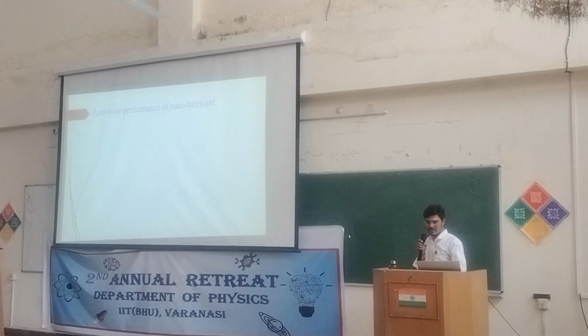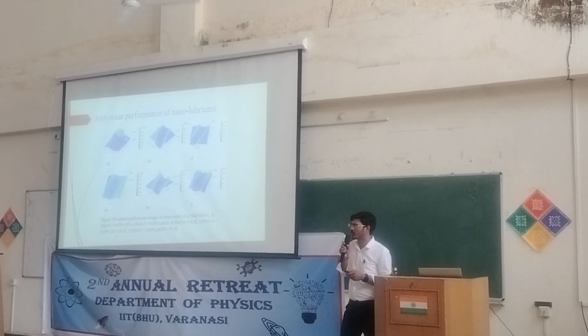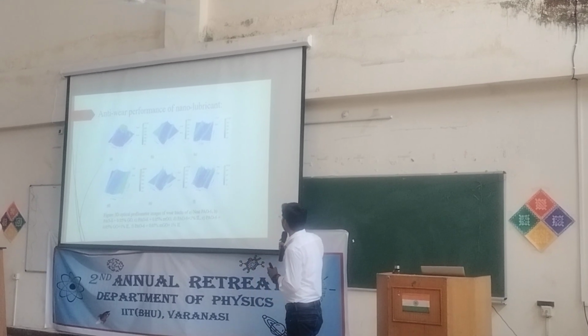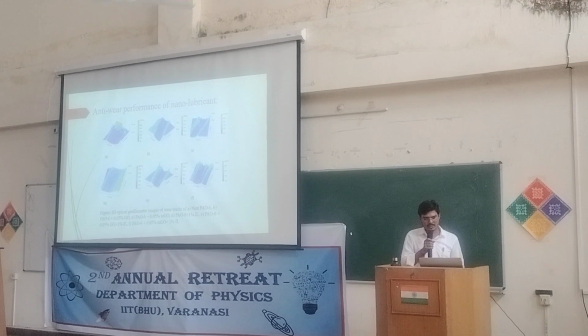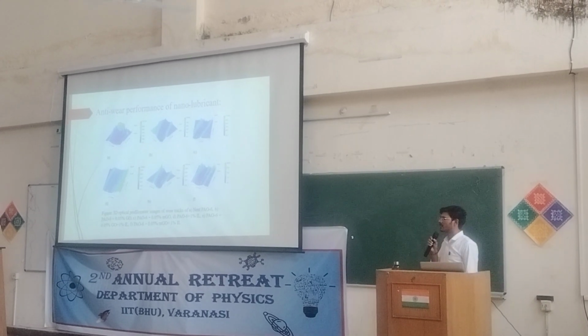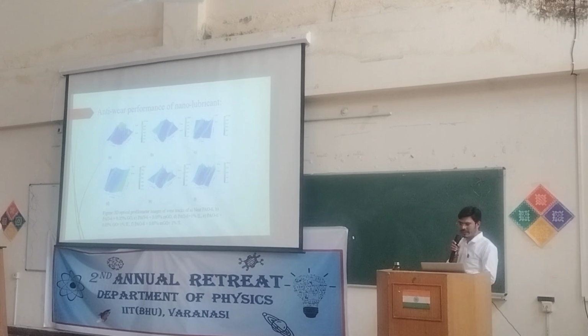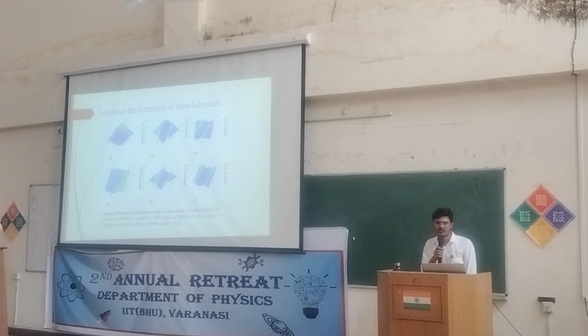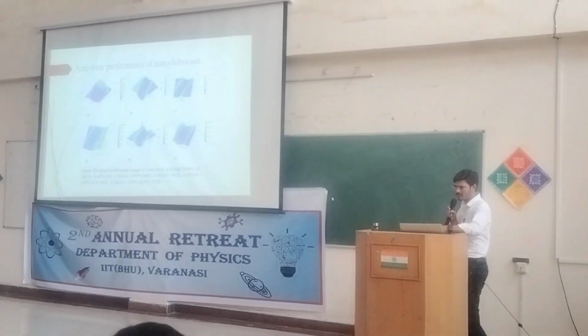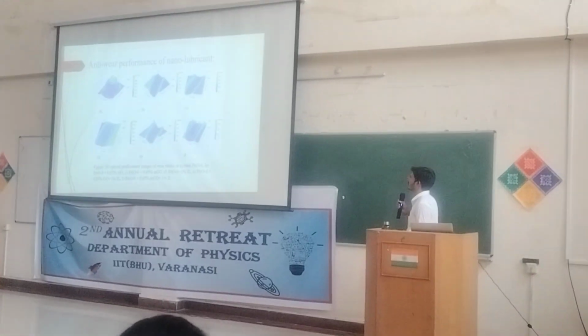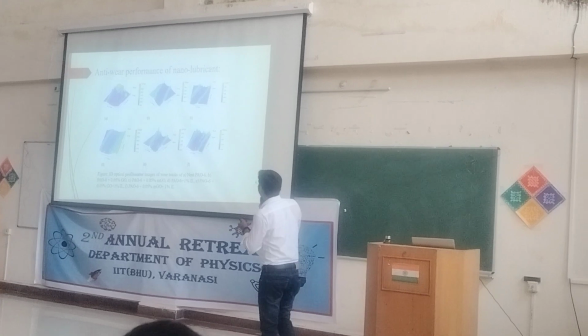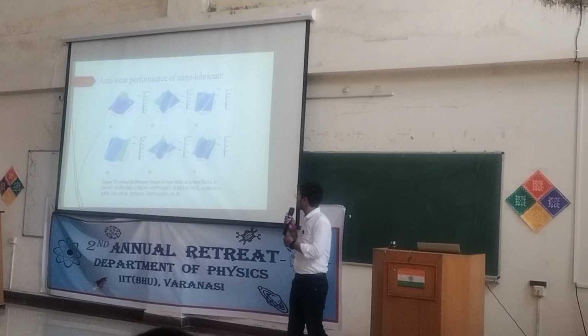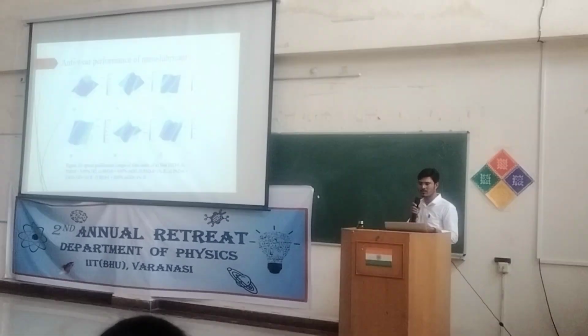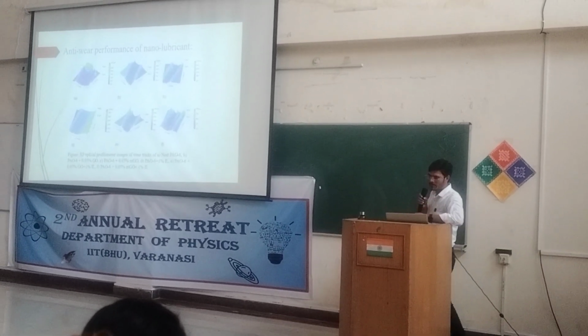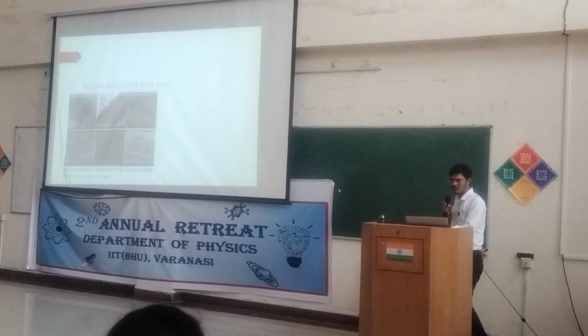And next, after studying the coefficient of friction, in the tribometer setup we get some wear scars on the disc by the reciprocating motion of the ball and disc. To study the wear scar profile, we use 3D and 2D optical profilometry, and by using different software, we can plot some line profile related to distance versus depth, or distance versus width of the wear scars. Here I have not shown the result, but I was able to reduce the wear by 42% in my previous research.